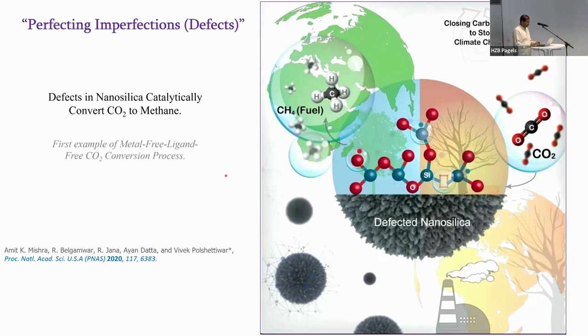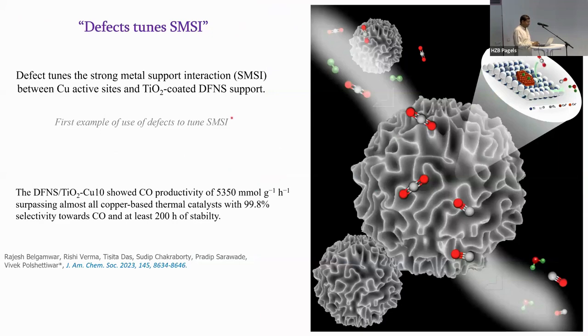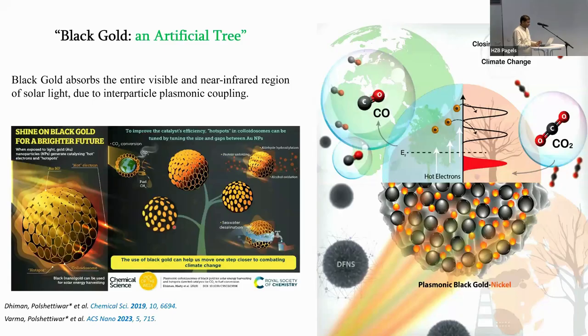So then we went back to the metal, but then we said, can we use the same defect concept to stabilize the metal sites so that they won't oxidize or they won't undergo sintering? So we then extended this idea. We created a defect in the TiO2. Now we coated the silica, we coated the DFNS with a thin layer of TiO2, and then we removed the oxygen from the TiO2. We have oxygen vacancies, and onto which we have copper sites now. So you stabilize those copper sites, and that allows you to then convert CO2 to CO with excellent productivity, as well as it's stable. It was stable at least for 200 hours, indicating that this could be another strategy to make a stable catalyst. I already showed you the black gold work.